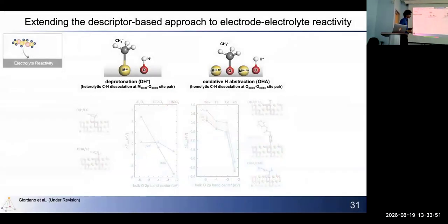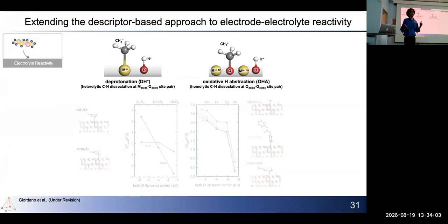The idea here was not to look at the complete reaction cycle, but predominantly the first step, which is an electrolyte reacting with the electrode. This is interesting because unlike in catalysis, here you want the opposite. You don't want your electrolyte to react with the electrode, because that will lead to decomposition and degradation of battery performance overall. So we are looking at an inverse motivation for studying this problem.